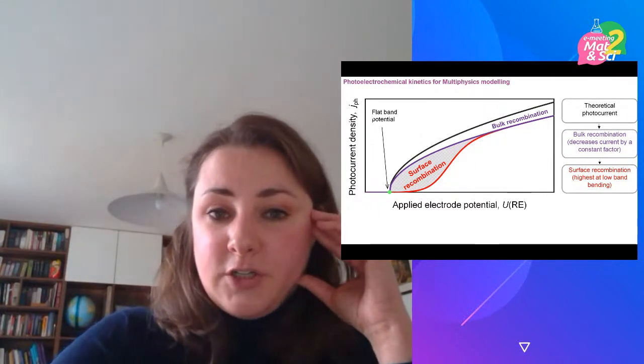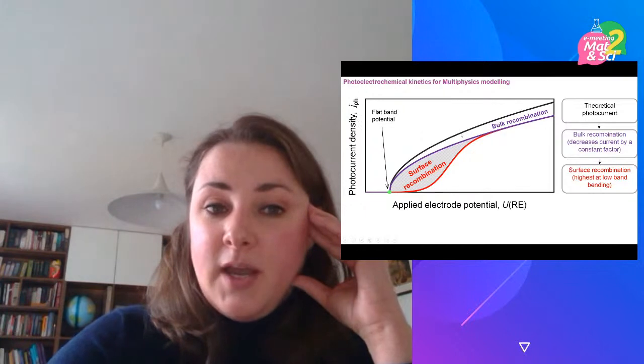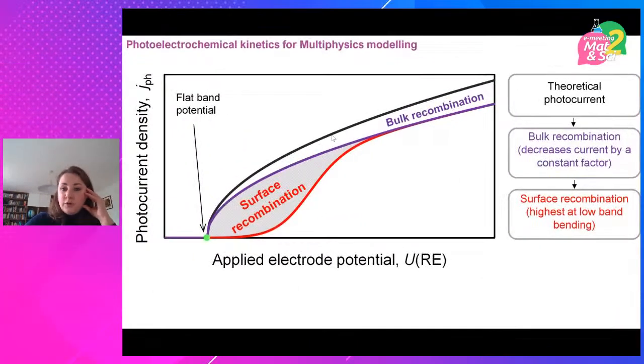So the theoretical predictions are represented here by the black line. And then you have two major sources of losses. So one is bulk recombination. So it's a constant factor by which the number of electron hole pairs are decreased in the bulk. And then you have something called surface recombination, which is dependent on the extent of band bending at the semiconductor liquid interface. So the higher the degree of band bending, the smaller the recombination fraction of charge. And of course, you want to minimize surface recombination and get maximum current out.